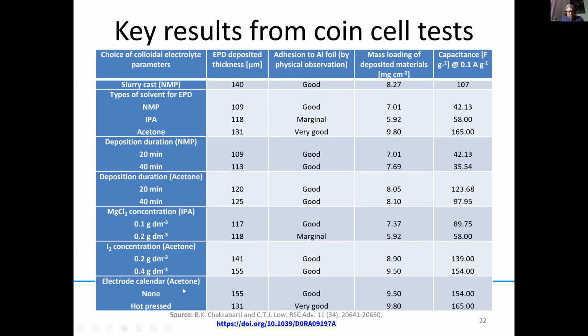However, for acetone, even without calendaring, we were getting pretty good capacitance and good mass loadings, and the activated carbon was sticking quite well to the surface of the aluminum foil. But obviously when we did hot pressing, the performance improved because of better electrical conductivity and connection with the aluminum foil, the activated carbon and the carbon black. So that's the optimized performance that we got with hot pressed acetone.